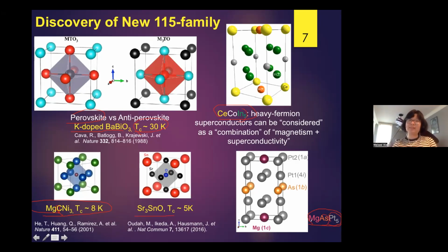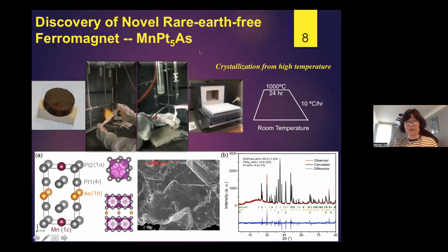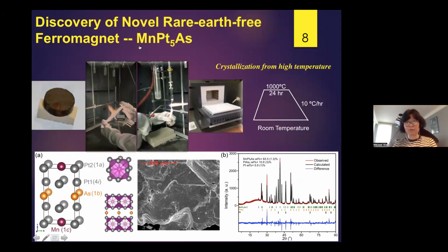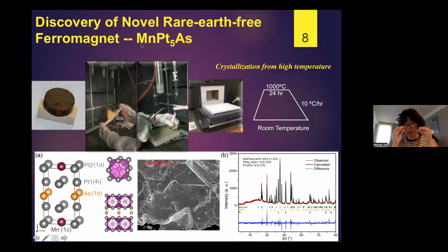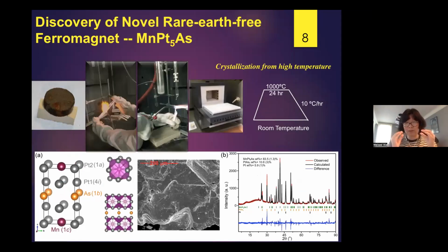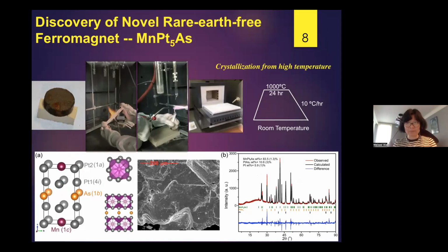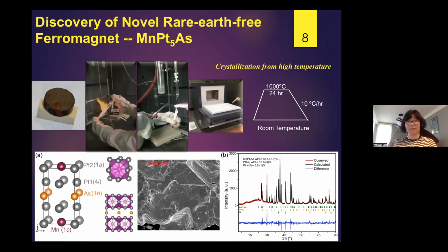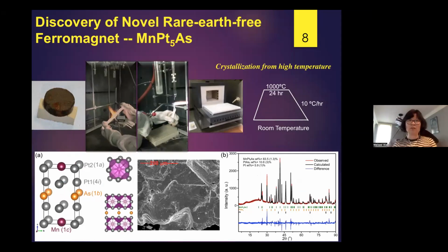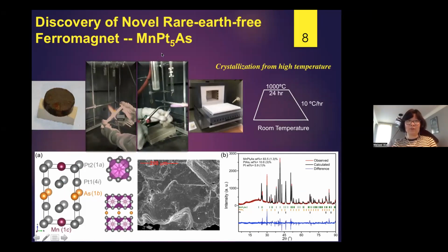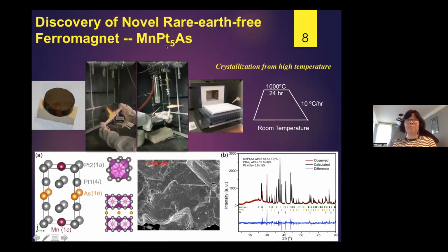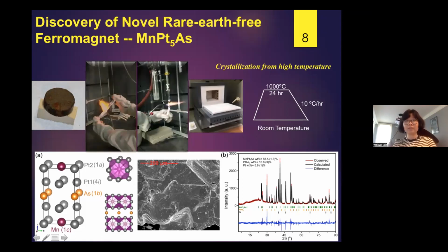In the beginning, we made this compound MgPt5As, and then we did the superconductivity test below 1.8 Kelvin. We went to 0.1 Kelvin, and we didn't see any superconductivity. So then I said, okay, how about we change to other elements? The first element we tried has a similar size; magnesium is usually 2+, and manganese also always shows 2+. We wanted to see if it has magnetic properties. Then we found a new material, a rare-earth-free ferromagnet, that's MnPt5As. So we made these compounds.